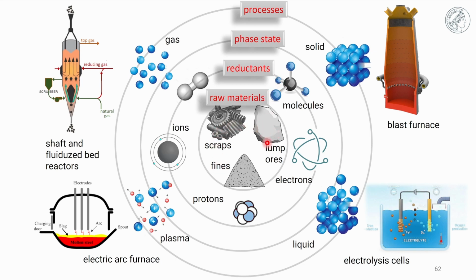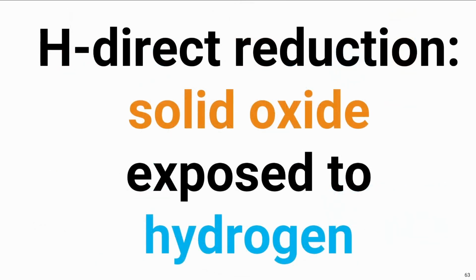In the center, you find the raw materials, scraps, fines, and lump ores, and you can subject them to reduction cycles with a couple of reduction means, like different types of molecules, like hydrogen or ammonia. You can use electrons directly, you can even use protons or ions. And they can have different aggregate states like gas, solid, liquid, or plasma. From these considerations, you arrive at a number of different possible processing pathways for how you can reduce iron. Each of these processing pathways, of course, has an individual energy, CO2 and hydrogen footprint that must be considered. Let me show you a few examples about hydrogen-based direct reduction of solid oxides that are exposed directly to hydrogen.